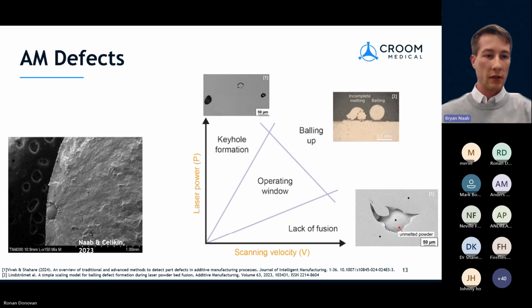Then I just want to discuss some of the defects which are found in additively manufactured parts. There's an operating window which we should try to stay within. Here is just an outline of what this looks like for a laser-based process. Essentially, we don't want to have too high of a laser power and too fast of a scan speed, and we generally want to be in that optimal sweet spot range. Otherwise, we're going to get formation of various defects, such as keyhole defects, balling up, or lack of fusion.